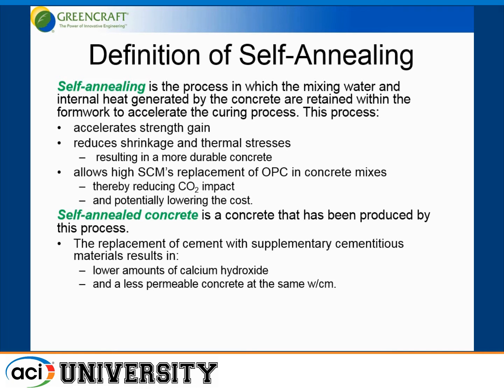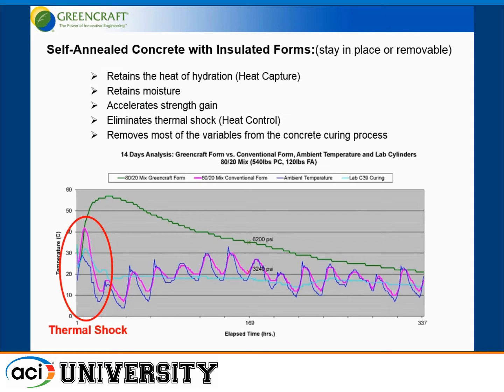The self-annealed concrete will help us with the supplementary cementitious material by eliminating calcium hydroxide and having a less permeable concrete with the same water cement ratio. So now we're taking the same concrete mix and we place it in the self-annealing environment. And how do we do that? Basically, we take insulation and we place it right on the surface of the concrete, visually, for an example, inside the formwork, if you will.